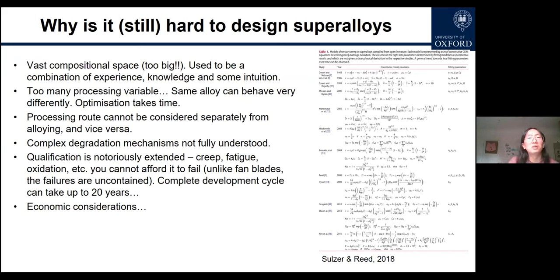Maybe we can now try to answer the question of why it is still very hard to design superalloys. On one hand, we have a very large compositional space, probably too big. How we designed in the past is using a combination of experience, knowledge, and some intuition and luck, to be frank. And also there are many processing variables. You can change the withdrawal rate. You can control the thermal gradient and thermal distribution in your furnace, and different heat treatment parameters, so that the same alloys can behave very differently. And the optimization will take time for a higher success rate. The processing route, of course, cannot be considered completely separately from the alloying development and vice versa. So they also have to match each other.